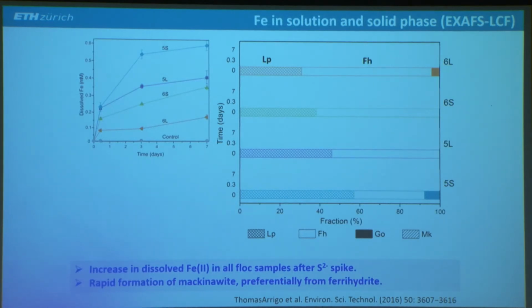Now, if we look at the iron speciation, on the left side, we see dissolved iron(II) in solution. And you can see that in all 4 flock samples, we saw a very strong and rapid increase in dissolved iron(II) in solution. The control had no release of iron, but the degree varied between the different flock samples. We look at the solid phase iron speciation. These are the initial speciation results.